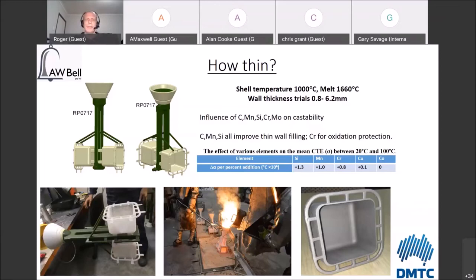So the effect of various elements on the mean coefficient of thermal expansion, you can see here that silicon, manganese, chrome, and copper all have negative effects on the coefficient of thermal expansion. Cobalt is generally considered to be 0. We did not add cobalt into these alloys that we looked at, the purpose being that cobalt is fantastic over temperature ranges of, say, room temperature upwards, but not so useful if you're going down to cryogenic or very cold temperatures, -150 thereabouts. It starts to not have a positive effect at those very low temperatures. So we left cobalt out on purpose.